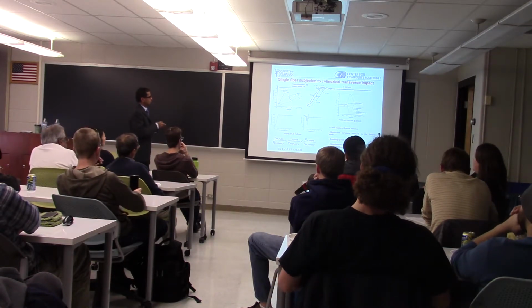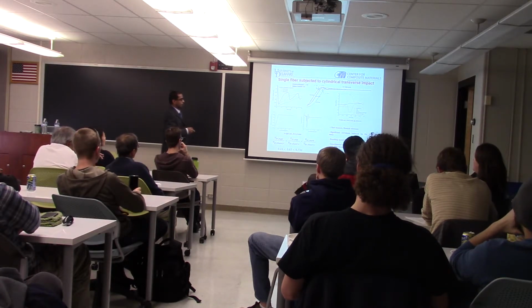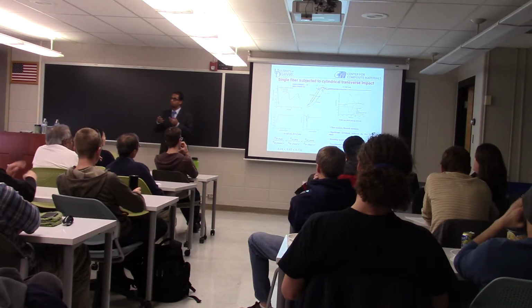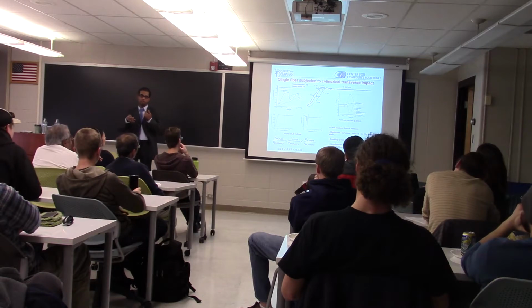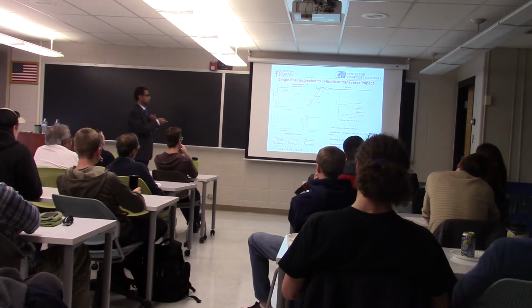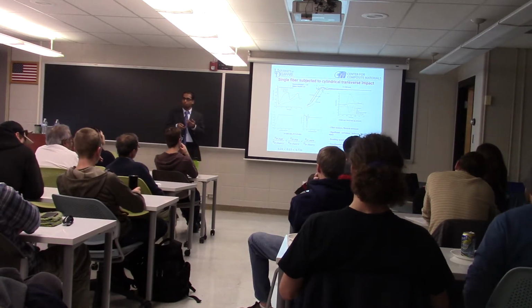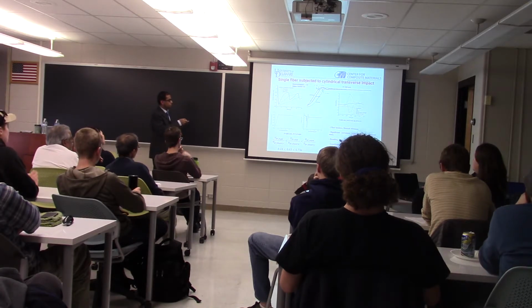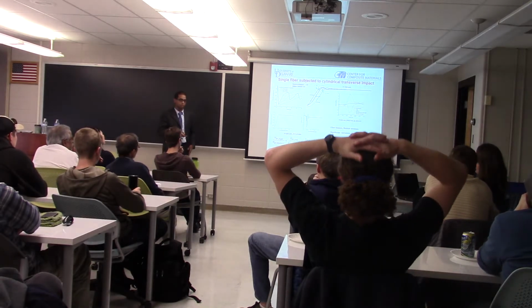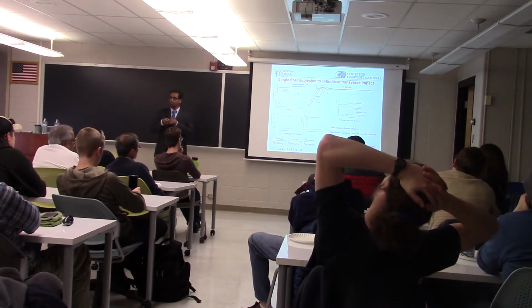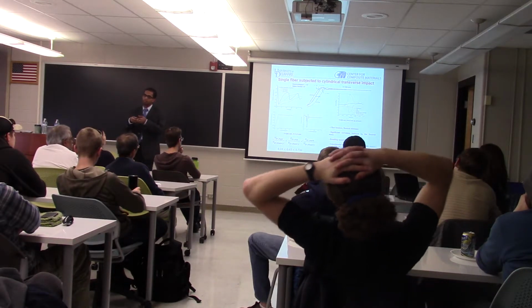So the theoretical upper bound for a linear elastic collision for an elastic material impacted by a massive rigid surface is 2. That is, the bounce velocity is 2 times the impact velocity. The models predict around 1.9 times the impact velocity. So this bounce effectively increases the strain in the material.